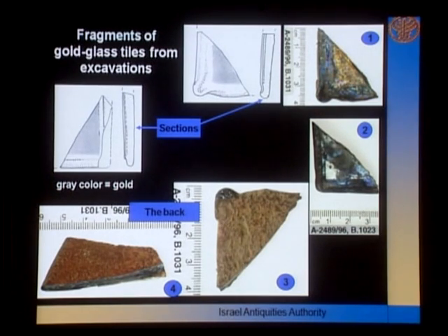We will now take a closer look at some excavated examples. They were made of 2 layers of translucent glass, usually colorless, and a thin gold foil in between them. The tiles were probably produced in several stages. First, the thicker bottom layer, between 5 and 8 millimeters thick, was made. Judging from the thickness of this layer and its coarse and dull back, it was sand cast. Then a thin gold foil was applied and immediately covered by a thinner layer of blown glass, less than 1 millimeter thick. Some tiles bear tooling marks on the corners, probably made by the pincers used to attach the thin layer onto the bottom one. Most of those found in excavations indicate the tiles were individually made.